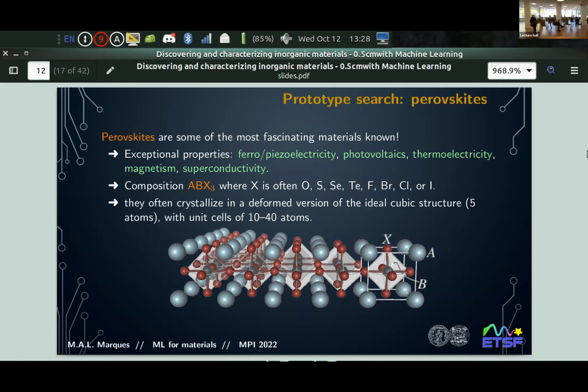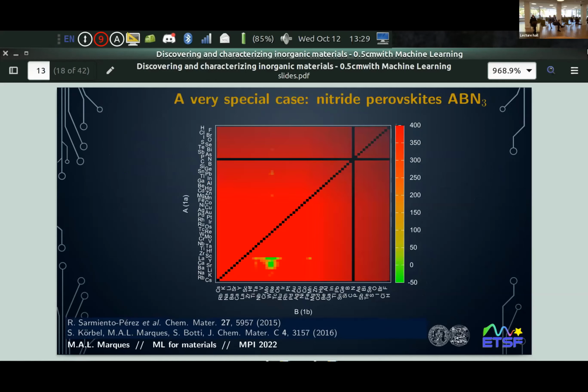But anyway, they often crystallize in a deformed version of this ideal cubic 5-atom cell. 5-atom cubic cell, that's easy, right? So we just run them all. There are around 500,000 possibilities, and the unit cell is relatively easy. We can actually run them all. I will not show you all the results because it's a bit too much. I will just show a very special case, these nitride perovskites. So you probably never heard about nitride perovskites because they actually didn't exist. And we just tried out of curiosity.